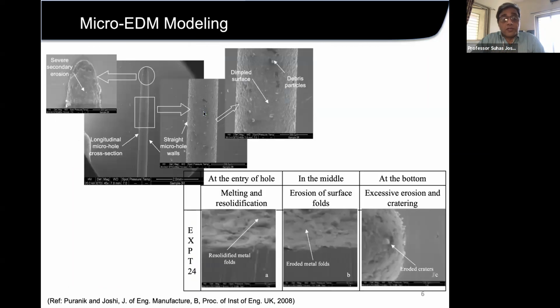Some of the holes which we opened, now we have the access to the holes which were machined, and we can do a lot of things. We can do scanning electron microscopy on the surfaces and see what happens. So you can see that this is the entry of the hole, and this is the end of the hole. The initial hole is very fine, but as you go down and down, you find that there are a lot of debris particles which are actually sticking to the surfaces, starting from here to here, and this is a further enlarged view.